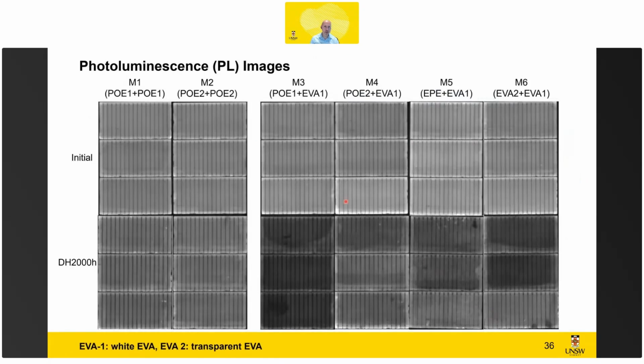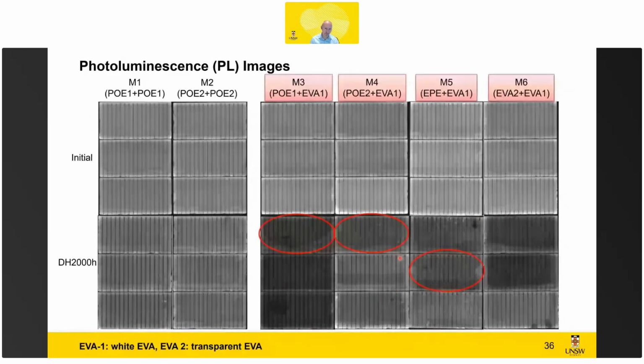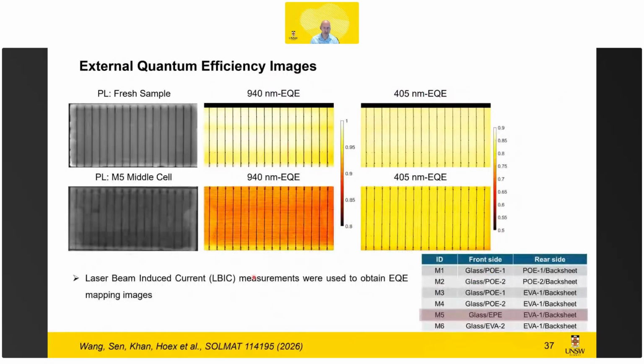So we looked a little bit deeper into the PL images again, and there we noticed two main takeaways. Indeed, them getting darker. In this case there was mainly the VOC reduction, but we also saw this interesting pattern appearing. So some parts seem to degrade less than other parts, and this varied a lot cell by cell. So that was what we investigated further.